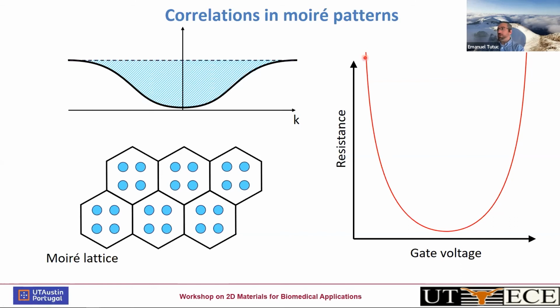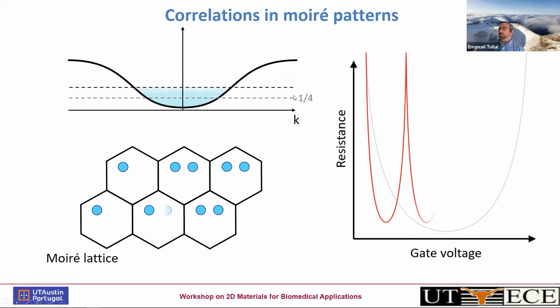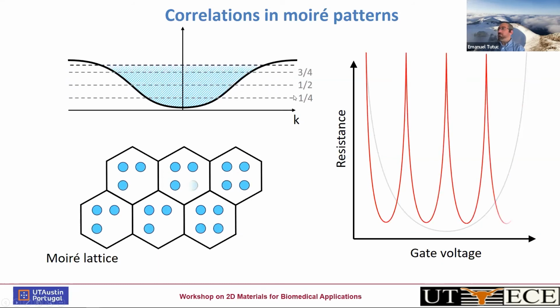And normally we would expect to see a resistance that changes with the gate voltage in this manner. At the bottom of the band, it would be large. In the middle of the band would be low. And again, the top of the band would be large again, because we have filled the band. Experimentally, what people see is that there would be insulators that actually emerge in the middle of the band. Why is that happening? So there would be insulators where there would be a large density of states otherwise.